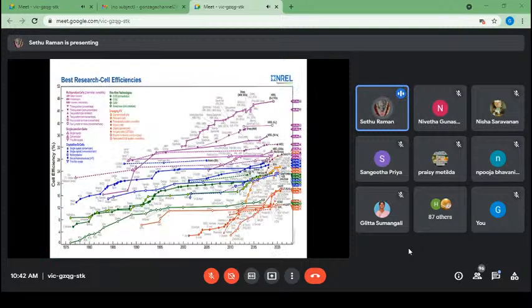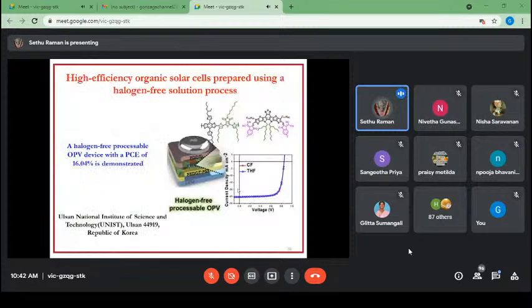Then this is a recent work, the highest power conversion efficiency prepared with long chain polymers using a halogen-free solution process. They synthesized a new material and used it with the halogen-free solution process, and achieved a power conversion efficiency of 16%. This work was published in the year 2021. And this is a small molecule, long chain polymer.